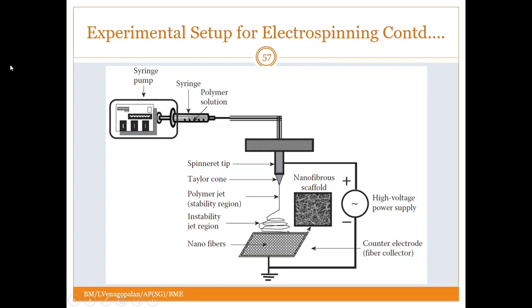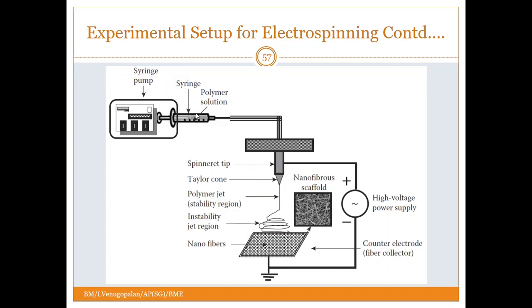So this is a typical setup. You have a syringe pump, and the polymer solution is pumped through the syringe pump. The polymer solution is filled in the syringe. This pump is a digital pump, so that would actually push the plunger, which would result in polymer traveling into the spinneret. The spinneret tip also forms a Taylor's cone in the end, and this is where you are applying potential. You are applying potential between the spinneret tip and the collector.